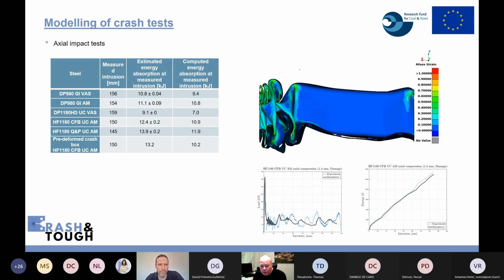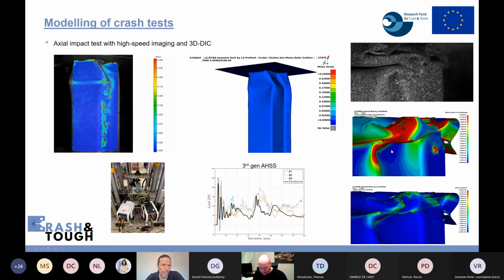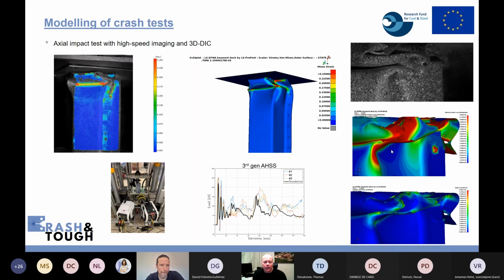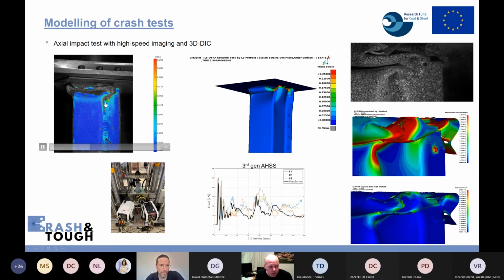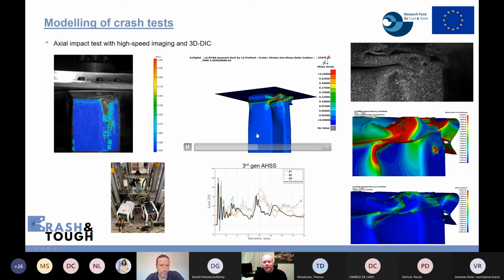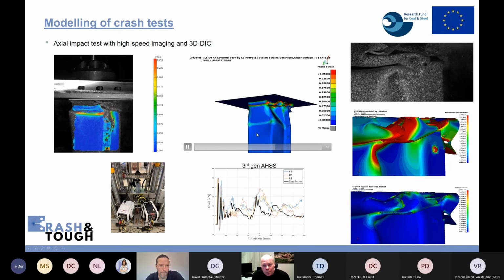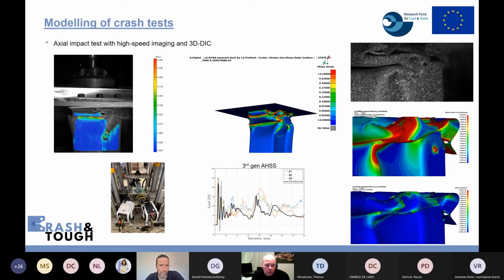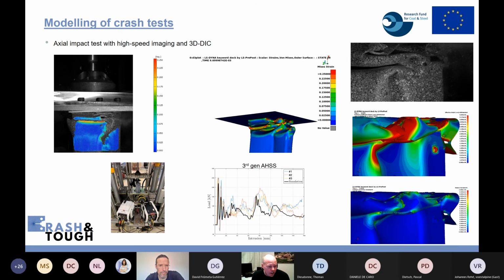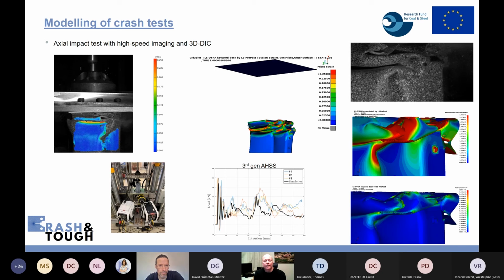Crash&Tough. And you can also see an example here for HF 1180 CFB, where the properties are underestimated. The calculated simulation is the black one, and the blue one is from the experiments. And another one, this is from LTU. You can see the measured strain to the left, and the video to the right is the corresponding model, and it looks quite similar, but the thing is, unfortunately, you only get the correlation until the crash box is too deformed.